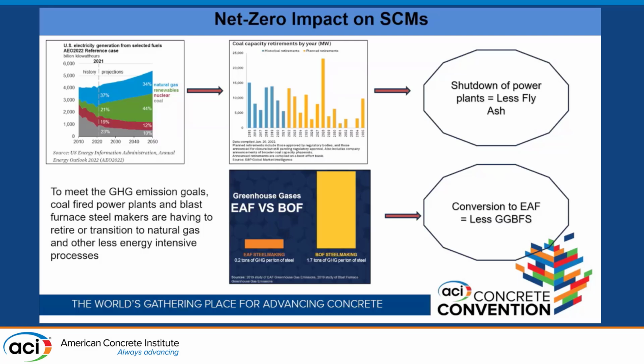Now, if you compare that to the slag situation, there's an order of magnitude difference between the blast furnace versus the electric arc furnace. This is forcing the steel producers to switch from blast furnace to electric arc furnace, which is leading to a shortage in GGBFS.